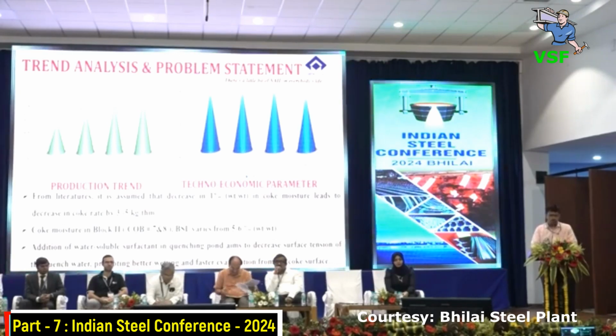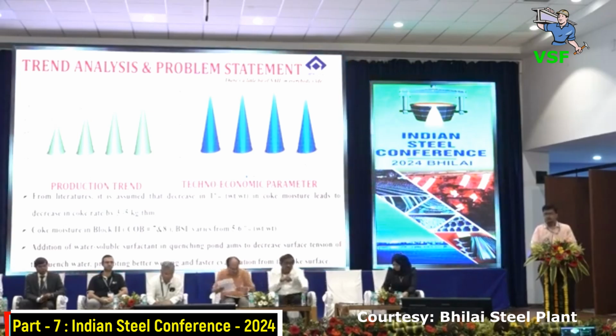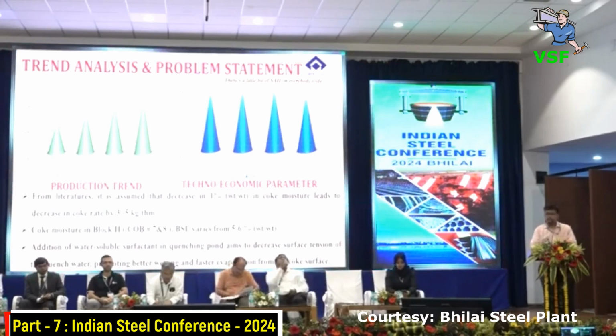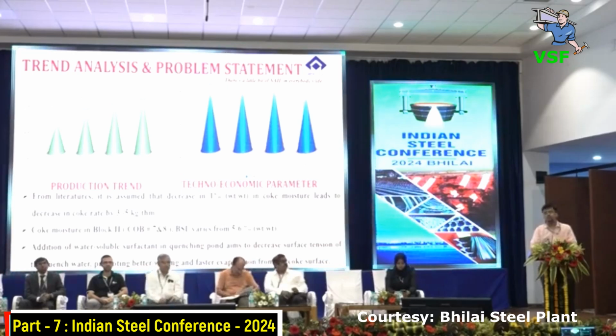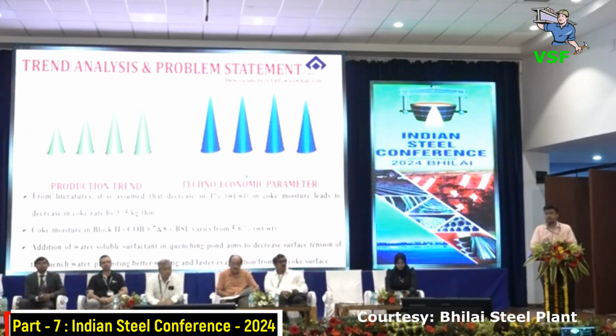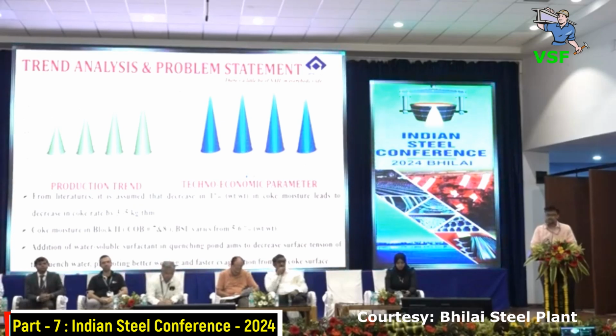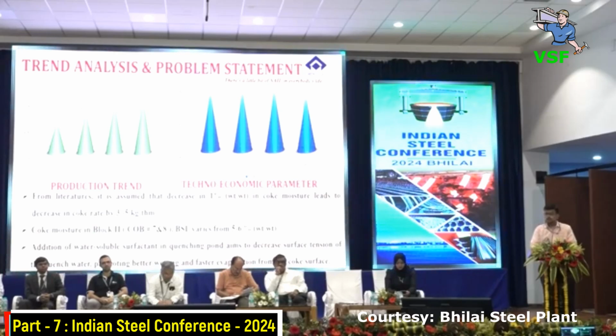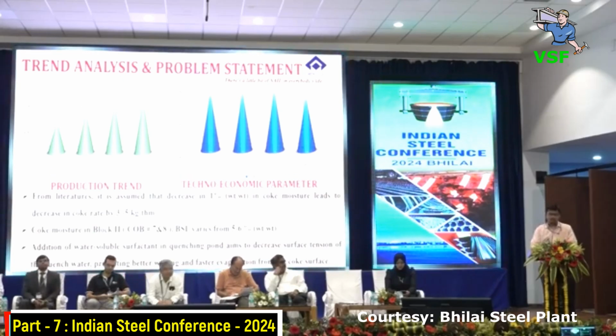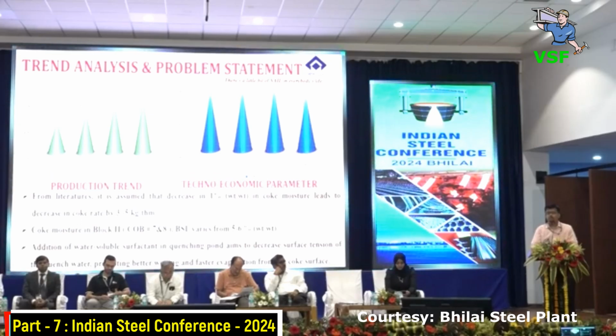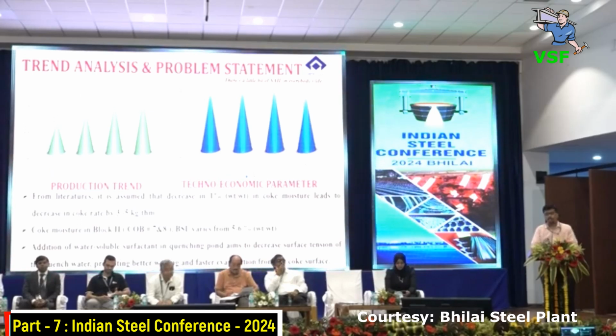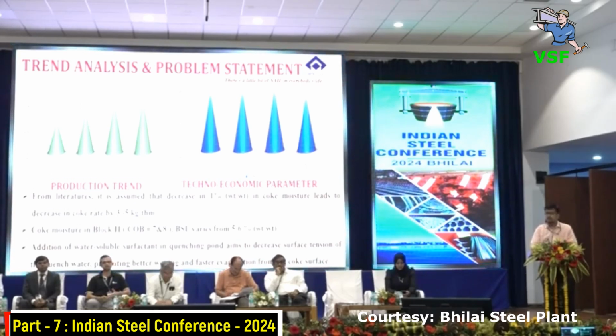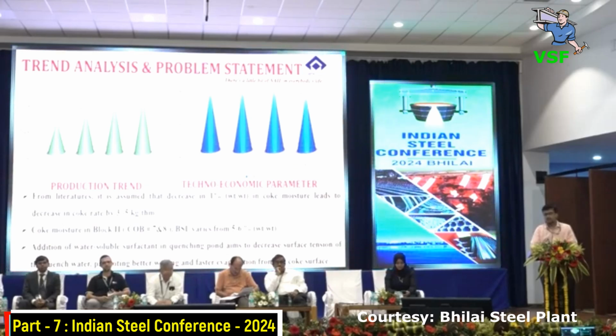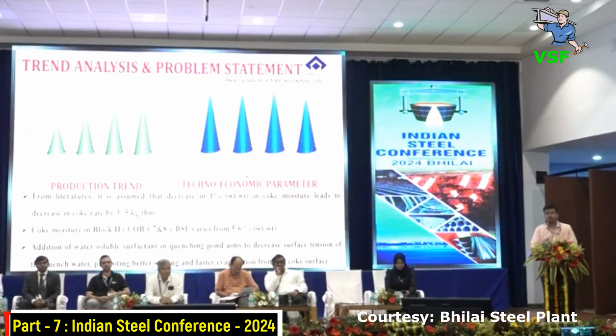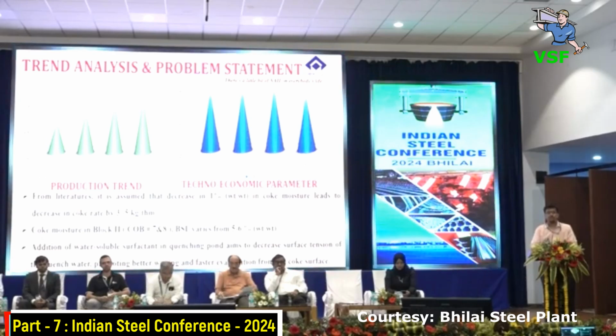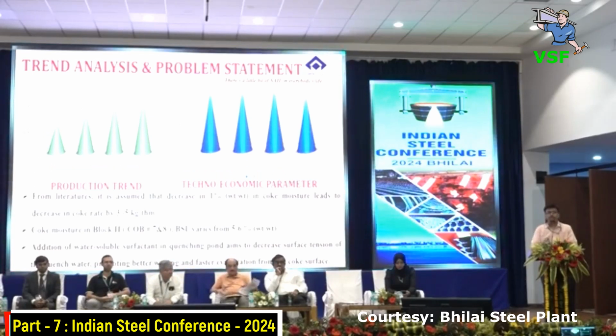Now seeing the trend analysis, comparing the production trend of ovens pushed per day, we see that there has been a gradual increasing trend from 421 ovens from 2020-2021 to 512 ovens pushed in 2023-24. And also seeing the techno-economic parameters trend of coke rate, we have seen that coke rate has gradually increased from 477 in 2021 to 487 kg per ton of hot metal in 2022-23, and then it decreased to 468 in 2023-24. As we all know that coke contributes significantly to CO2 emission as well as the cost economics of hot